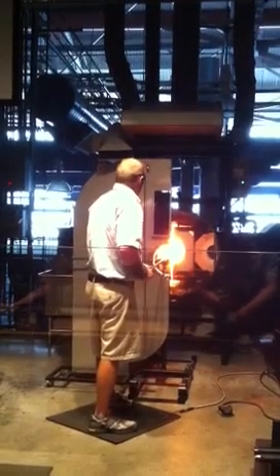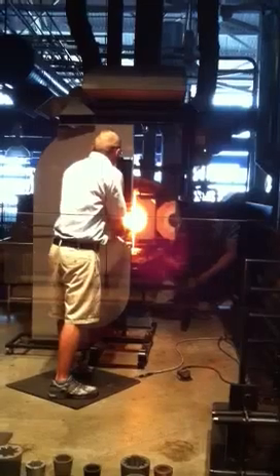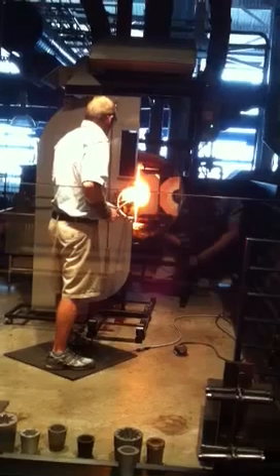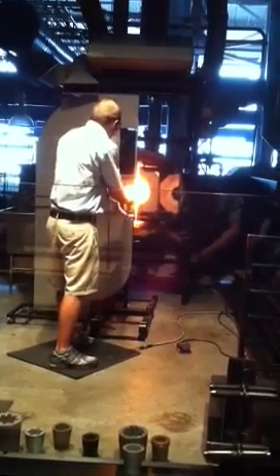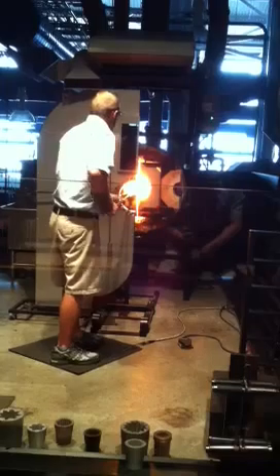You must be wondering: if we have to keep everything above 900 degrees, how do we save anything we make? The process is called annealing. Anything we make, we have to slowly cool down. A piece of this size is going to take about 8 to 10 hours. By slowly cooling the glass, we give the thick and thin parts — the surface and the core — a chance to cool down evenly so that they shrink evenly.